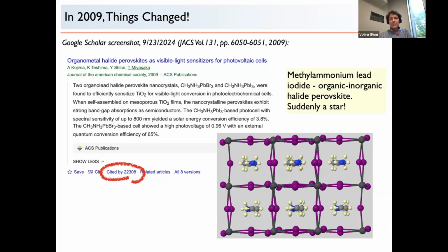You can see that the lead atoms, which are the gray atoms here, and then the iodine atoms are coordinated octahedrally around them, and then there's an organic cation, methyl ammonium, and you see a series of them here behind one another. That is the functionality. But you can make similar materials in other dimensionalities.